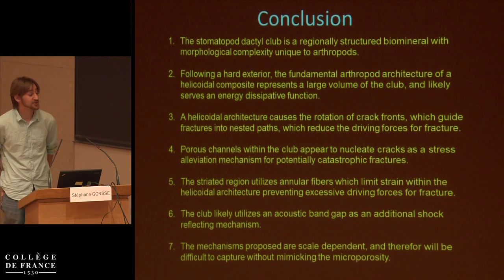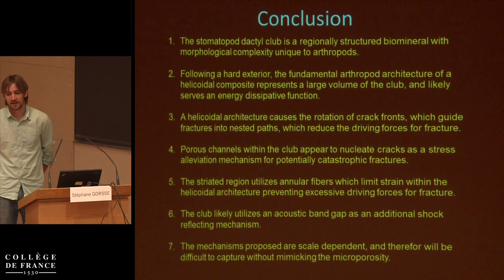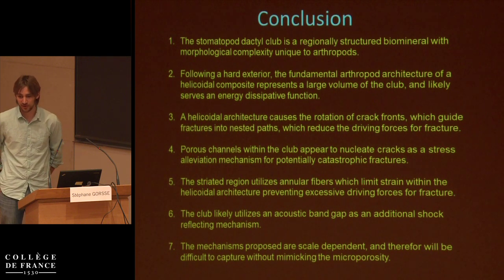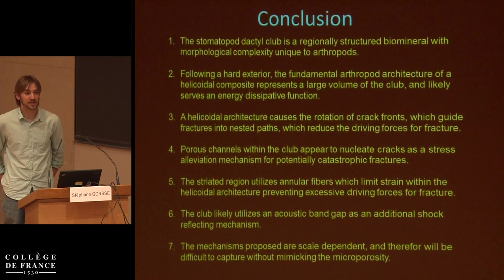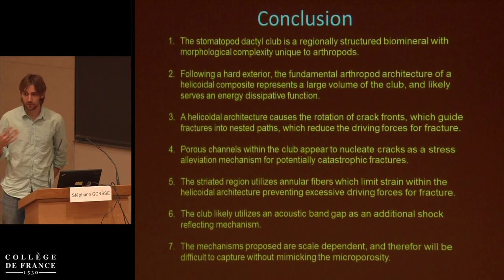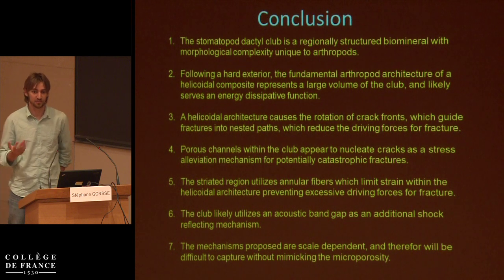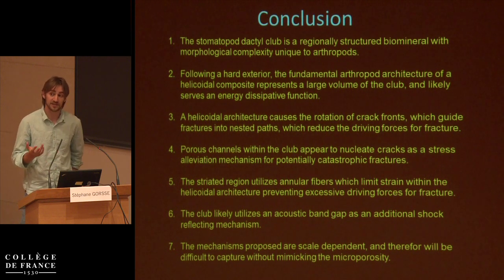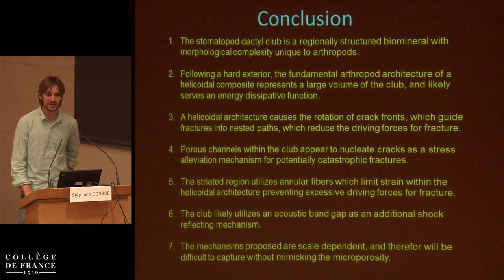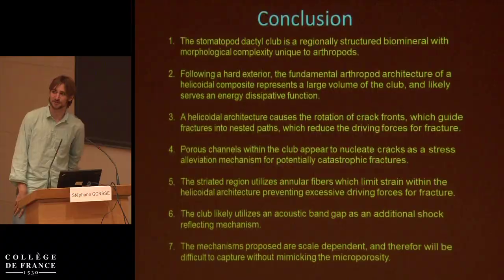assuming this hypothesis is true, one thing that you would predict is that everywhere that you find helicoidal composites, which is all over nature, you would also find 5 to 10 micron spaced microporous channels. And that seems to always be the case. But I won't steal Ron's thunder, but it appears that there's actually more than one way to concentrate stress than just avoid. So that's a teaser for Ron's talk.